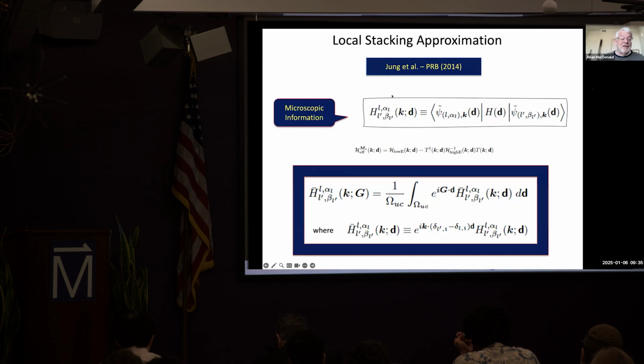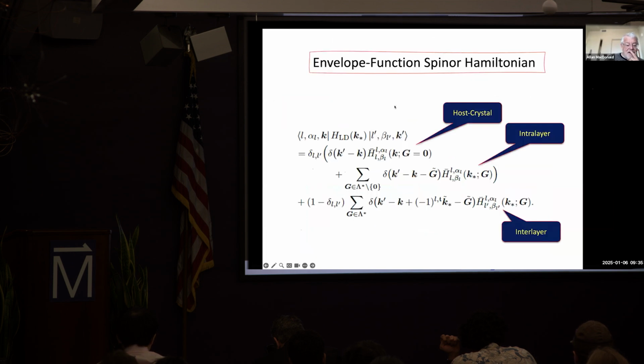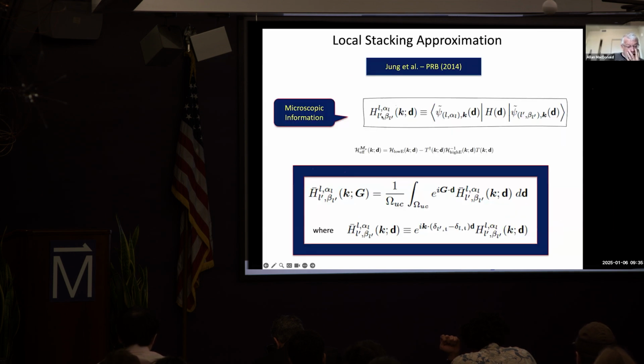And in some problem, by layer, you have Wannier functions. You have some set of orbitals that are important in a certain range, and you can calculate what the Hamiltonian looks like as a function of displacement between the layers. Okay, so that's the microscopic information in this approach that you get from doing a DFT calculation.